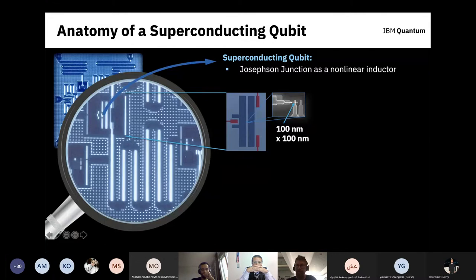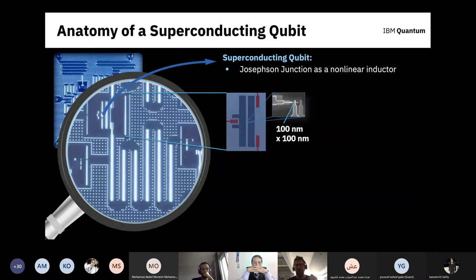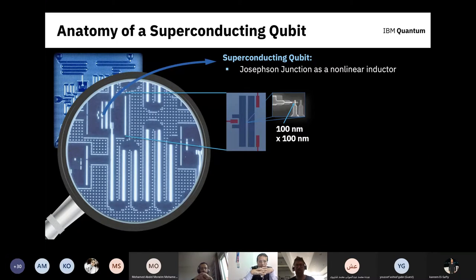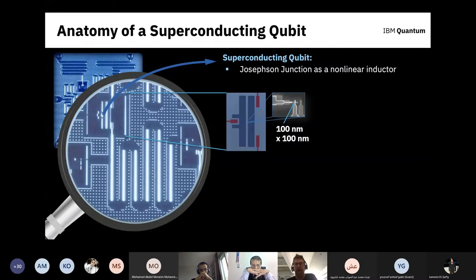This special element is called a Josephson junction — a superconductor-insulator-superconductor structure. Specifically, aluminum, then aluminum oxide as an insulator, then aluminum again. Aluminum grows a very easy-to-fabricate oxide even though these junctions are 100 nanometers by 100 nanometers. Standard techniques in university labs can fabricate these — they've been around for about 50 years. Their key property is that they act as a nonlinear inductor, and that nonlinearity is one of the keys to making a qubit.